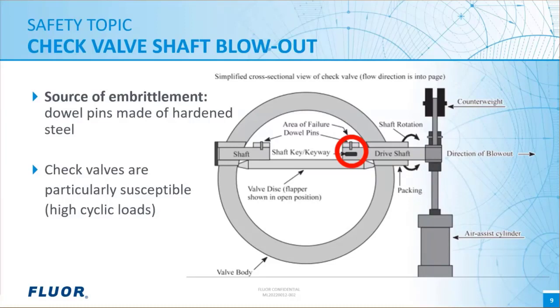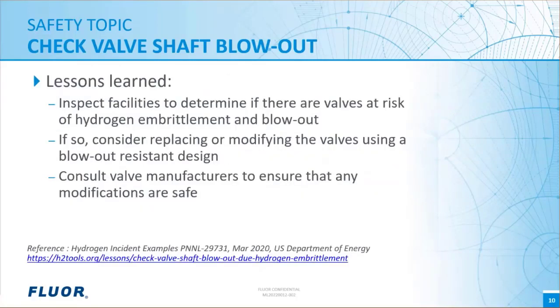And it's also worthwhile to note that check valves and butterfly valves are particularly susceptible to this condition because of their geometry and because they typically undergo higher cyclic loads from having to open and close more frequently. And so from this incident, there were a few lessons learned. For one, it's important to inspect hydrogen facilities to determine if there are valves that are at risk of hydrogen embrittlement. And if so, consider replacing or modifying the valves using a blowout-resistant design.